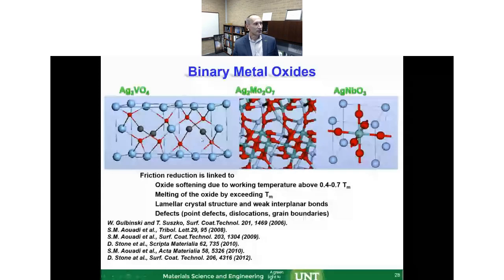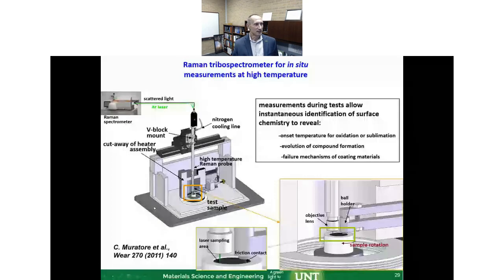They also looked at where metallic bonding exists rather than covalent or ionic bonding, so you can identify this type of oxide. One of these silver vanadates came out as one of the winners, and then experiments were set up to track it. The problem was that it forms at a fairly high temperature, and at moderate temperature a different oxide forms. So we also needed a tool to be able to detect it.